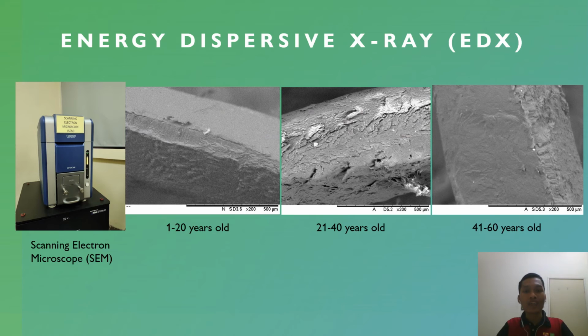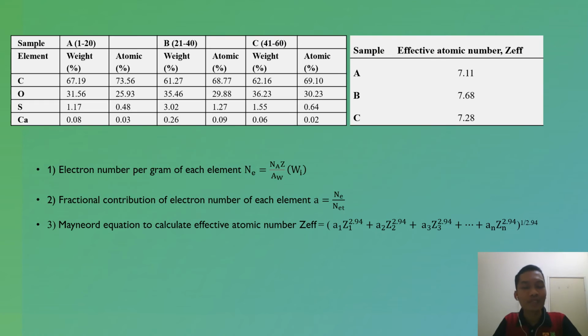For the purpose of EDX analysis, a scanning electron microscope was used to obtain the image of our sample at a magnification level of 200 times, and these were the images of the 3 samples which were all non-irradiated. The scanning electron microscope also provides us with the information of elemental composition in the fingernail itself, and from this information we can calculate the effective atomic number according to these 3 steps, and from the 3 samples we can conclude that the effective atomic number is approximately 7 in all 3 samples.